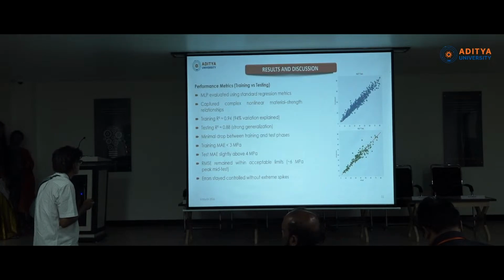Results and discussion. Performance metrics. MLP evaluated using standard regression metrics, captured complex nonlinear material strength relationships. Training R square is equal to 0.94, 94% variation explained. Testing R square is equal to 0.88, strong generalization. Minimal drop between training and test phases. Training MAE is less than 3 MPa. Test MAE is slightly above 4 MPa. RMSE remained within the acceptable limits.